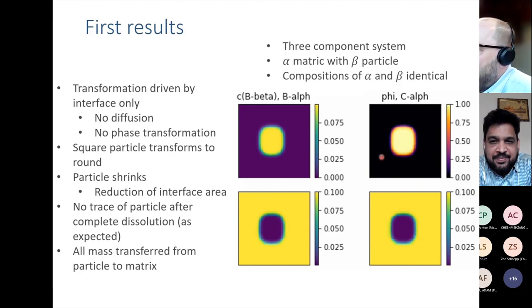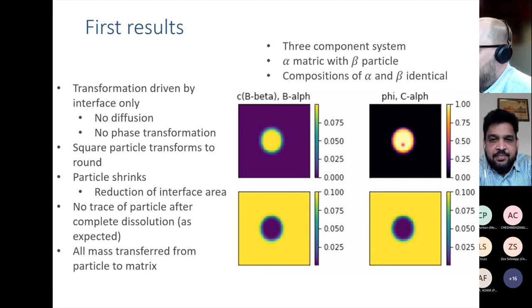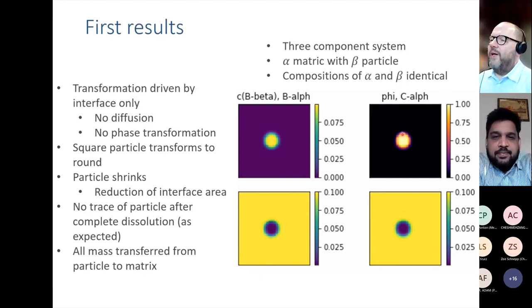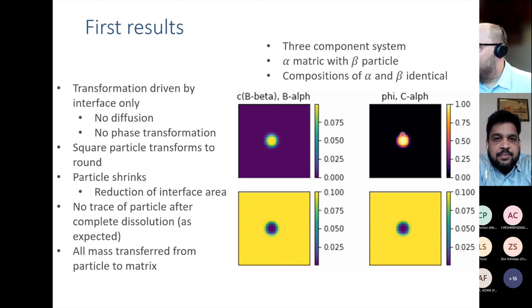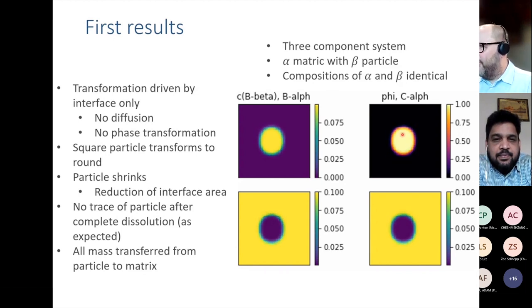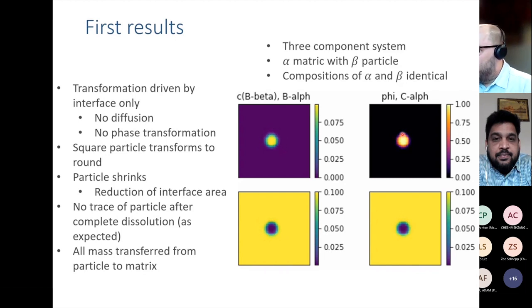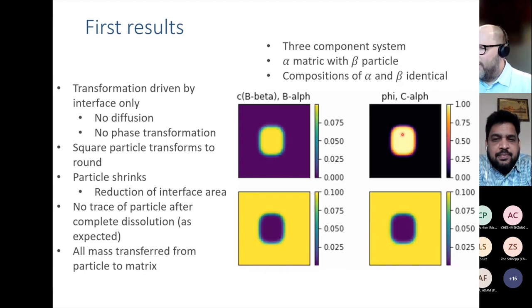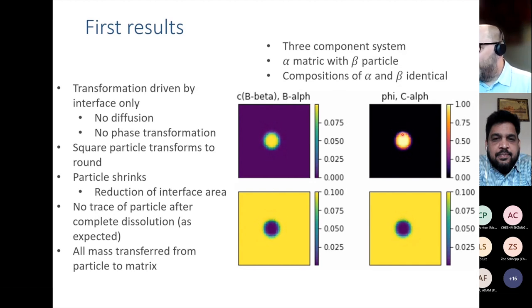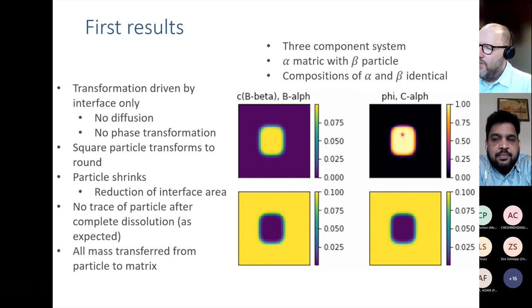So here we have a particle. You see here is the order parameter. The particle is at the same composition of the matrix. And all I'm doing is now applying the curvature. So just the interface, which is working towards shrinking the particle, and then use the reaction rate step in order to redistribute elements in that spirit and find how does the matter in the particle redistribute. And as the particle is at the same composition of the matrix, we find once the particle disappeared, there is no trace of the particle.